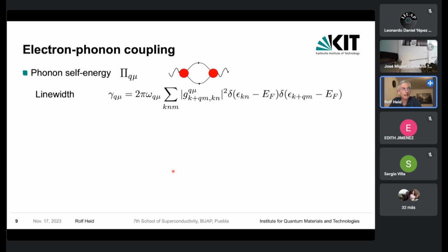Here is now the first application of a quantity which can be calculated within this scheme. That's, for example, the phonon self-energy. And this represents such a kind of process where a phonon, so to say, is virtually decaying into an electron-hole pair. And the imaginary part of this quantity gives us the line width of a phonon, which is in principle a measurable quantity. And in this formalism, this is just given by a sum, or actually an average of this electron-phonon coupling vertex matrix elements squared over electronic states at the Fermi level.